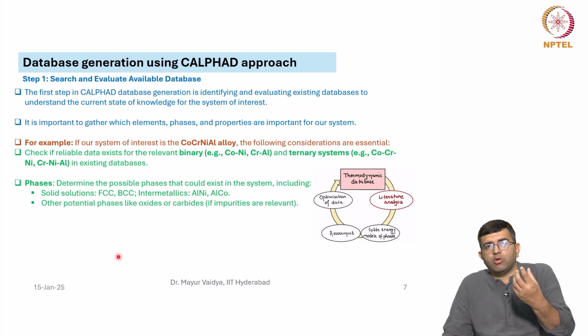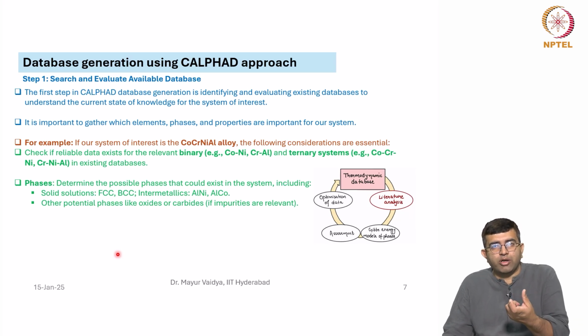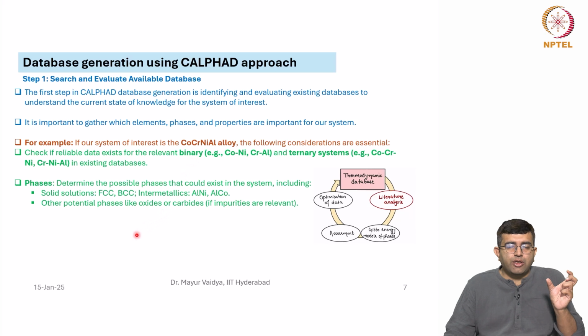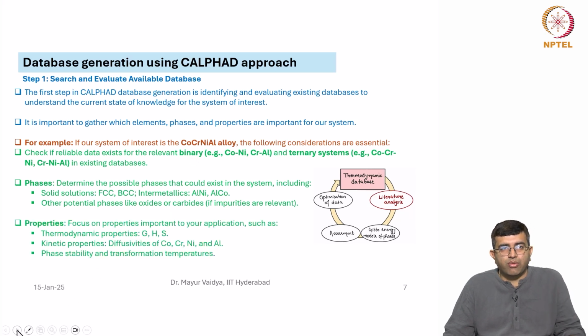So, say you are processing by a method where carbon contamination or oxygen contamination is unavoidable, then you may want to look for a database which contains the information about oxides and carbides in addition to these elements, so that you have the prediction about that as well.